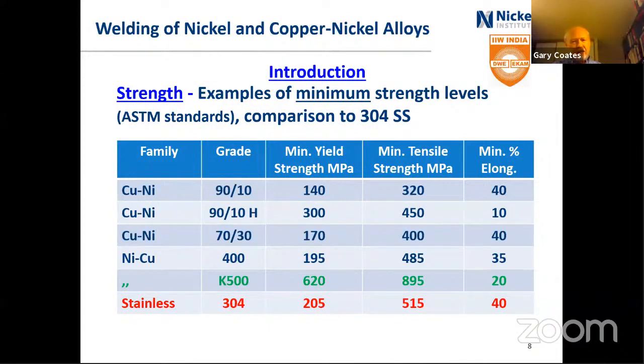Because of that, the elongation, really indicative of the ductility of it, is lower, still reasonable, but not as good as the annealed materials. Now, there is a copper nickel grade, a 90/10 grade, that is work hardening, that has a much higher strength. It isn't used a lot, and because it is work hardened to get the higher strength, again, when you weld it, you're going to affect that property, at least in the heat affected zone. And so it is commonly not welded. It is used more for springs and certain other equipment, bar material perhaps.